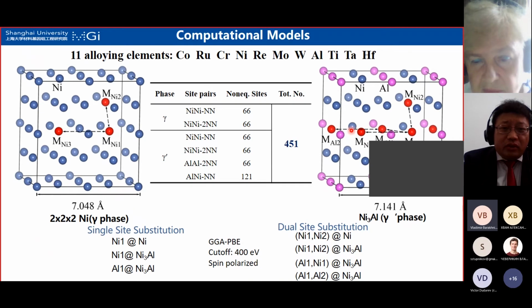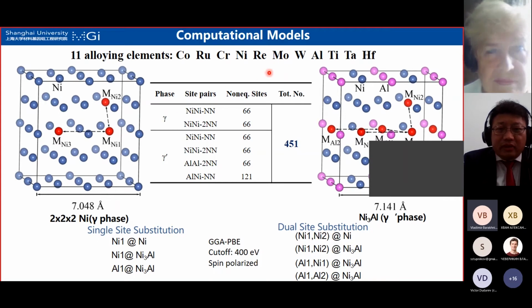First, we need to do the computation to get the data. In this case, we have 11 elements, which are common elements in single crystal superalloy. We started with two substitution sites, either in the gamma phase or gamma prime phase, because these are the main phases in nickel-based superalloy. We replace nickel or aluminum with the 11 elements. So there are a lot of substitutions, and the number of combinations is huge in principle.